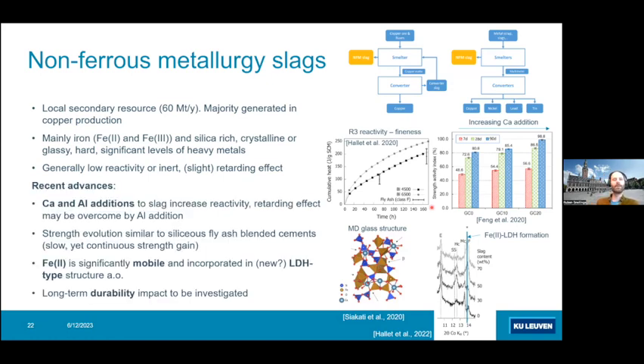Recent advances go a bit along the line of what we've seen for steel slags, so trying to modify the composition of the slag at a high temperature by adding in calcium and aluminum will have a massive effect on the reactivity. So you will actually create a more reactive material. And also, if you then quench the slag, so making it amorphous, then you will retain reactivity and strength contribution. Typically, this strength contribution would be comparable to siliceous fly ashes. But on the other hand, you resolve the issue that many of these slags actually don't have applications at the moment. It should be said, of course, that they have significant levels of heavy metal. So if you can also reduce heavy metal leaching, or you can recover heavy metals at the same time,